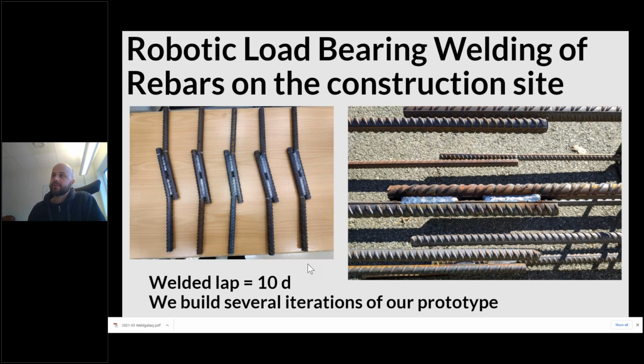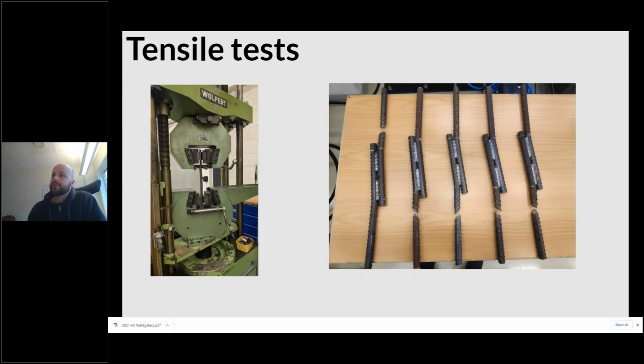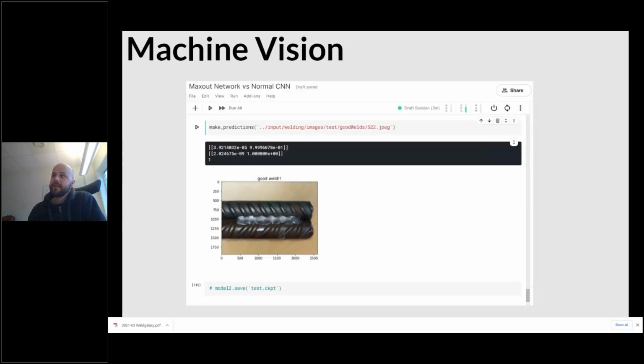And the nice thing is, one of the main reasons to weld them is that you can reduce the lap lengths a lot, to 10 times the diameter, if they're welded properly. So yeah, then I told you we bent them a little bit so that they fit in the machine. Those are tensile tests we have run, and it's nice because they didn't fail in the weld.